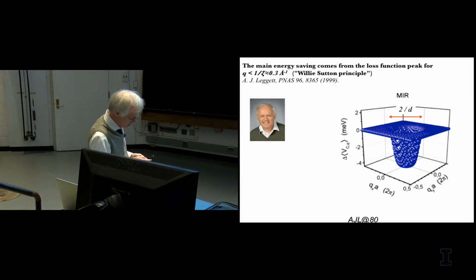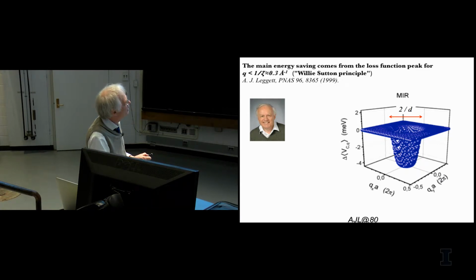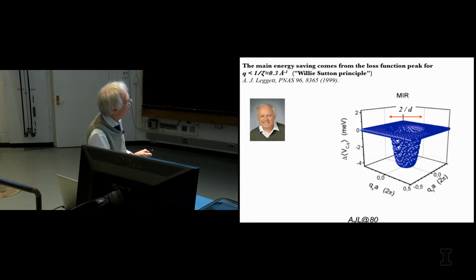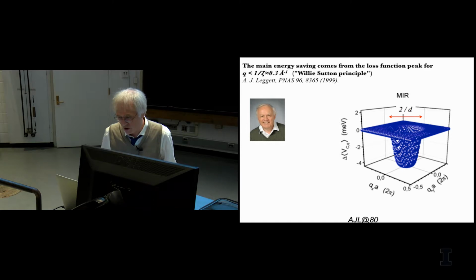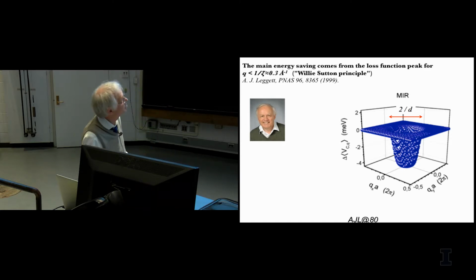There we have to go really into the details of Leggett's idea. He said, well, in principle, this Coulomb energy change that you measure at Q equals 0 is more or less what you would have for all values of Q parallel to the planes up to a certain limit, which is 2 divided by the distance between the planes.